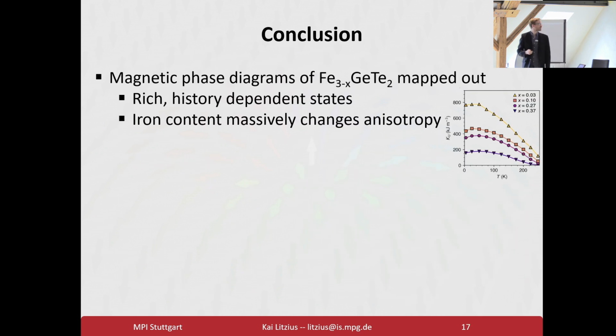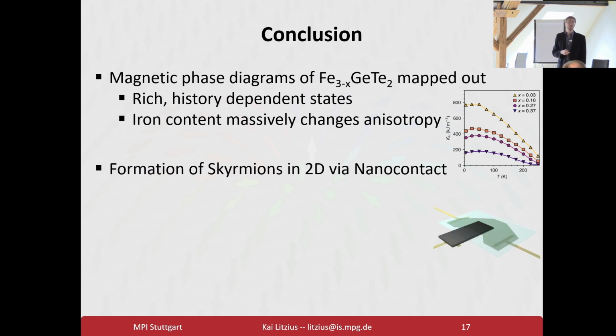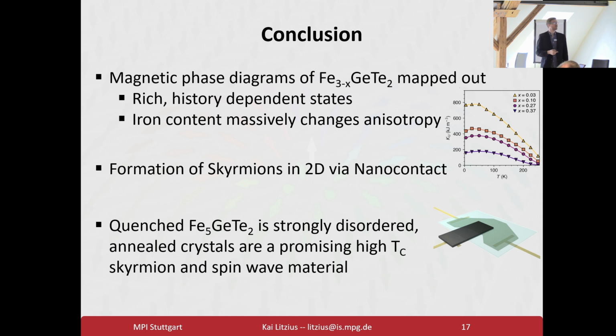All right, so let me conclude. We've got magnetic phase diagrams investigated in different compositions of iron germanium telluride. The iron content seems to be massively changing anisotropy in the material, and therefore can be used to tailor the magnetic states. We've got an idea of how to prepare 2D capable skyrmion writing devices by nanocontact current injection in van der Waals flakes. And I showed you that the quenched Fe5GT systems are massively disordered, or can be massively disordered at least, and needs to be checked very thoroughly, while the annealed ones seem to be perfectly suited for spin wave and skyrmion applications. All right, thank you very much for your attention.